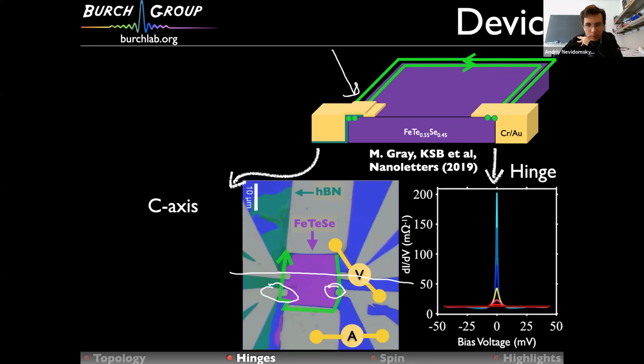Yes, I think so. So the reason is that there's this HBN here, right? And that's equivalent to this HBN. It's very thick HBN, I should say. It's not thin. So there's no tunneling through the HBN. It's just an insulator that allows us to cover up the hinge and make an identical contact to the bulk.